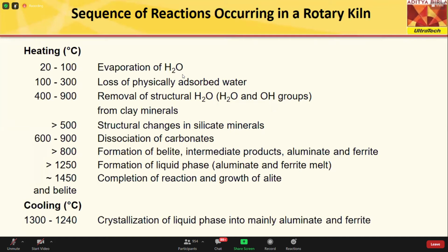So formation of liquid phase starts after 1250 degrees Celsius. These aluminate and ferrite melt, and in this molten mix, the C2S combines with available free lime to form C3S. And at around 1450 degrees Celsius, this process completes, and alite, that is C3S, tricalcium silicate, is formed, which is mainly responsible for initial strength. Then cooling starts in the cooling zone and then in the cooler.